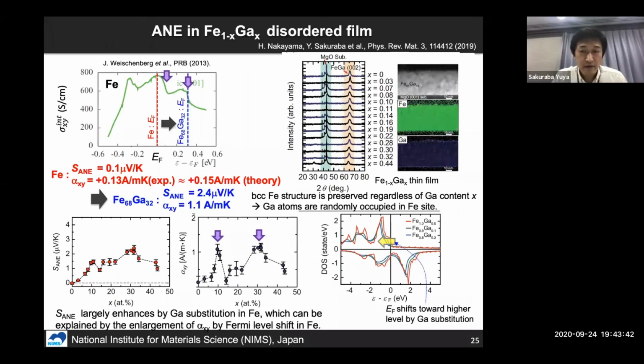Yes. Of course we check the deposition rate of, for example, the iron and iron gallium targets, control the power for each target, and design the composition ratio. But sometimes a deviation between the designed composition and the actual composition happens. So we check the composition by XRF for each film.